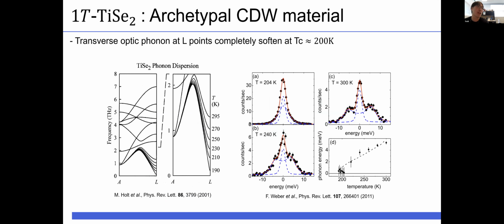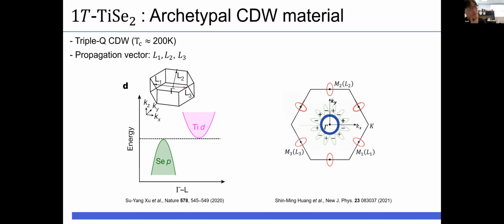In the right figure, Frank Weber and collaborators observed the complete softening of the L point phonon by inelastic X-ray scattering. When the phonon freezes, the displacement is induced along the phonon eigenvector. So the original CDW is charge fluctuating at the L points. In the band structure, there is a hole pocket at the gamma point and an electron pocket at the L points. The charges at the gamma points and L points fluctuate, and this charge modulation is coupled with the phonon at the same Q points, the L points. It generates a structural phase transition.